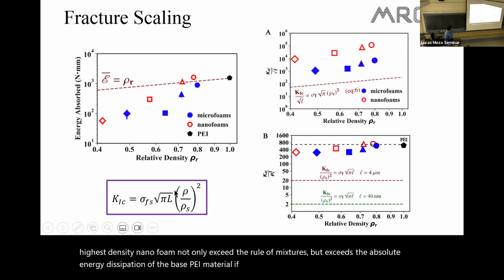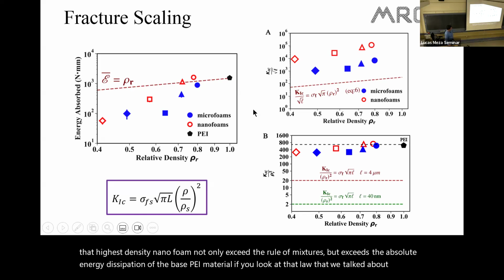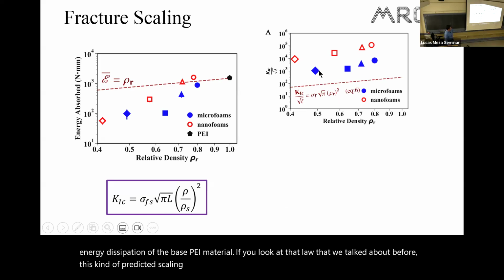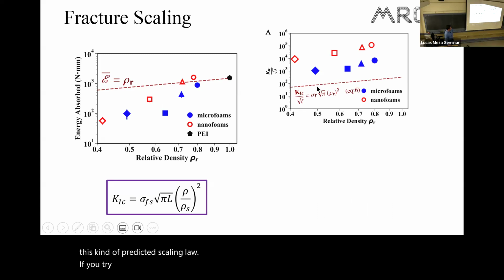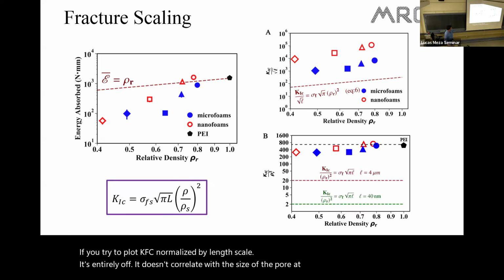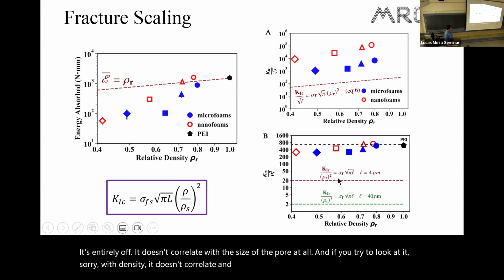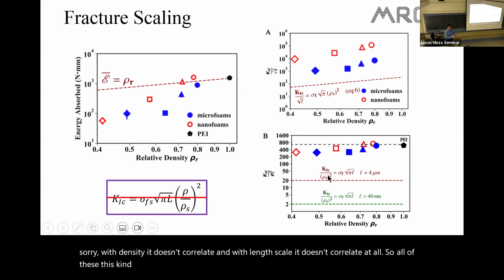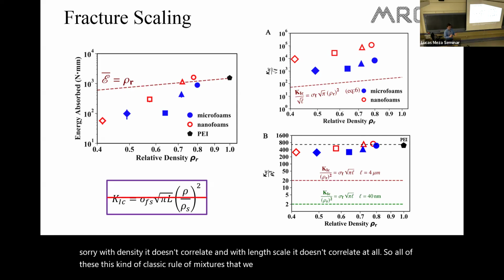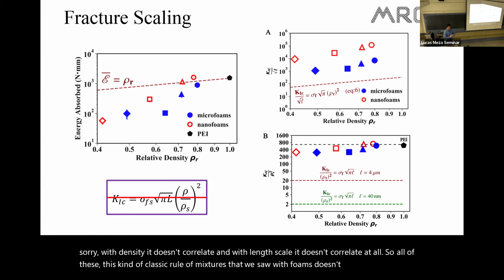If you look at that law that we talked about before, this predicted scaling law, if you try to plot KIC normalized by length scale, it's entirely off. It doesn't correlate with the size of the pore at all. And with density, it doesn't correlate, and with length scale, it doesn't correlate at all. So this classic rule of mixtures that we saw with foams doesn't apply for these micro and nanofoams.